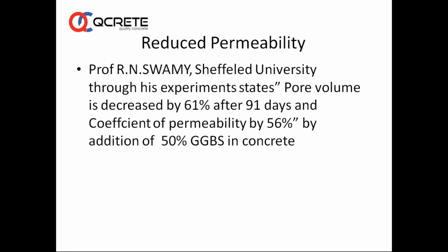And these CSH gels will go on filling up the capillary pores. We already talked about the capillary pores, different types of pores and all. So it will go on filling up these, and as the concrete ages, the pore volume decreases. Professor R.N. Swamy has talked about this. The pore volume is decreased by about 60% in 90 days, and the coefficient of permeability is reduced by about 56% by addition of 50% GGBS. As I said, the concrete is made denser as the capillary pores go on getting filled up by the usage of SCM, when the SCMs go on reacting with the calcium hydroxide and causing more and more calcium silicate hydrate gel formation.